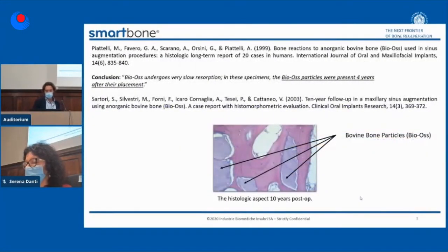So here we can see some results from papers. In the case of the Bio-Oss product, the first on the right side of the previous slide, if we perform a histological analysis, a biopsy, after 10 years, you can see that there is no remodeling. You can see some bovine bone particles still in the body. The new bone can grow around these particles, but there is no possibility of a complete remodeling.